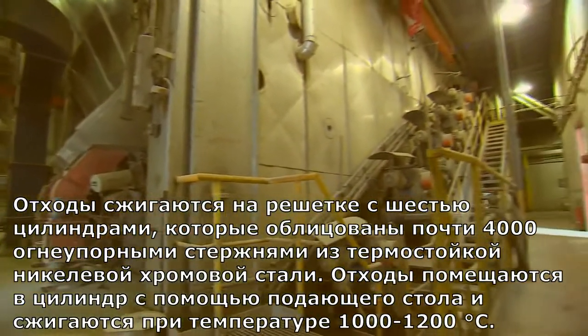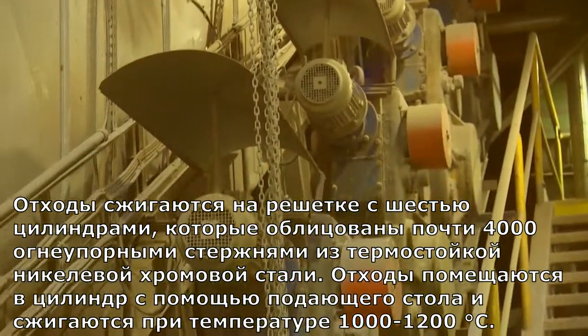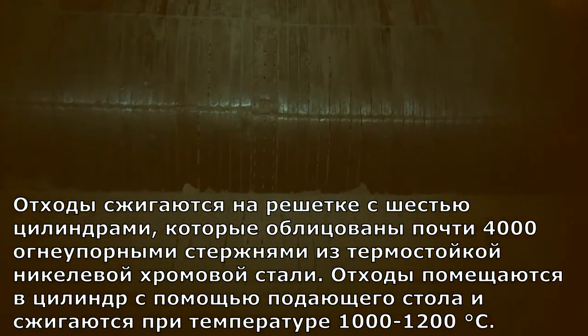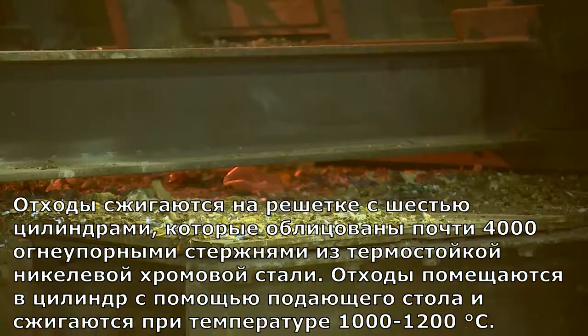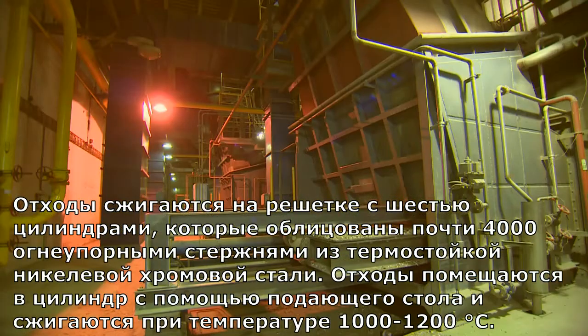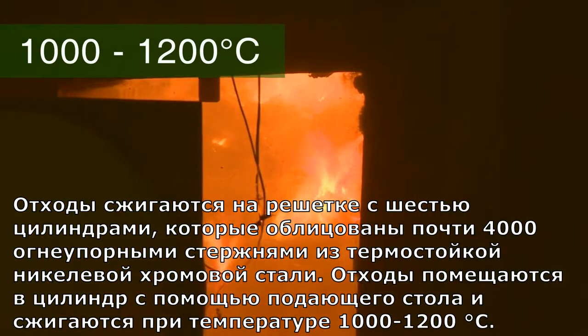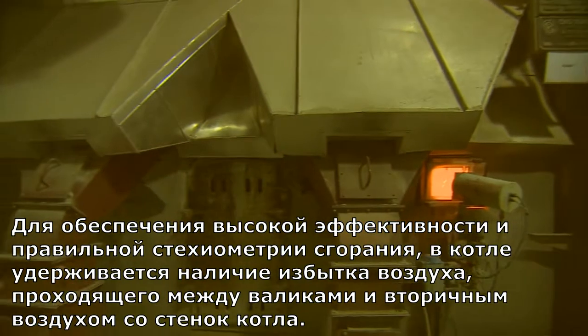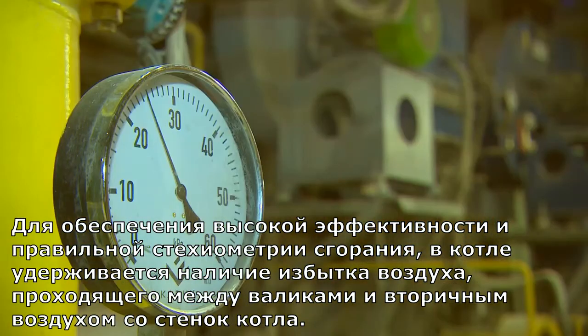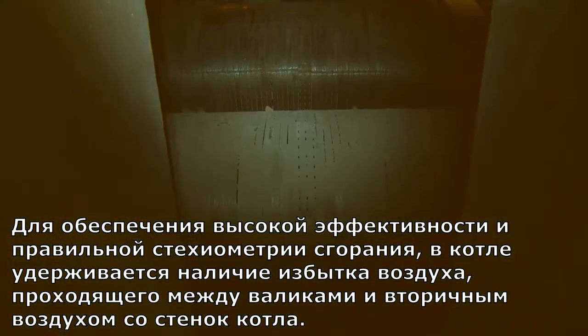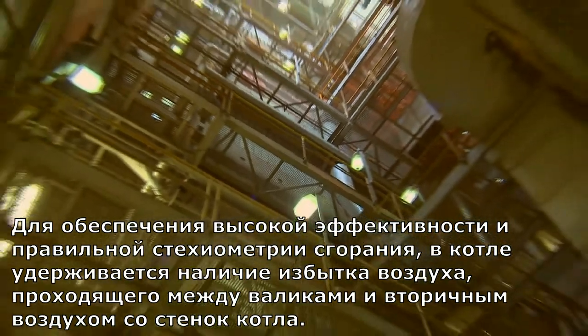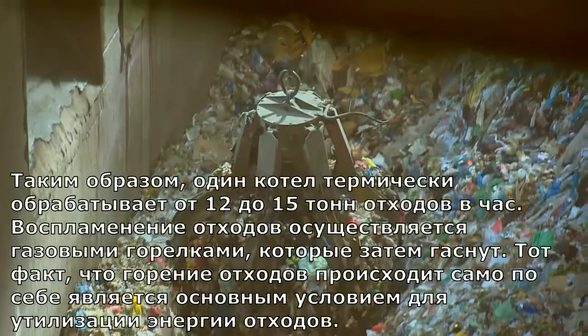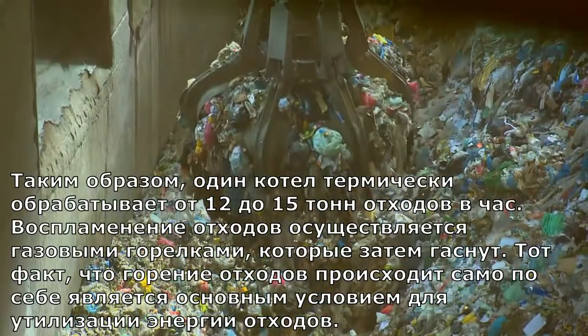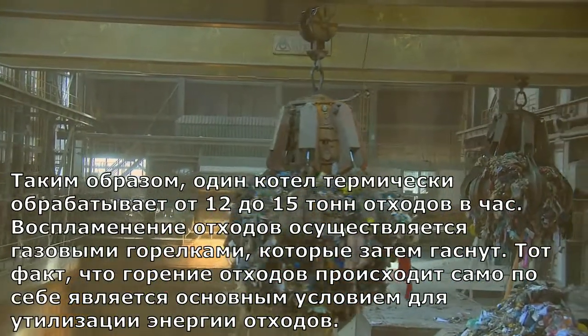Waste is burned on a grate with 6 cylinders which are lined with nearly 4,000 fire grate bars made of thermally resistant nickel-chromium steel. Waste is stoked up to the cylinder by means of a feeding table, and there it's burned at a temperature of about 1,200 degrees Celsius. To ensure high efficiency and correct stoichiometry of combustion, there is a surplus of air in the boiler, which is blown into the boiler by the slits between the rolls and the secondary air from the boiler walls. This way, one boiler thermally uses between 12 to 15 tons of waste per hour.